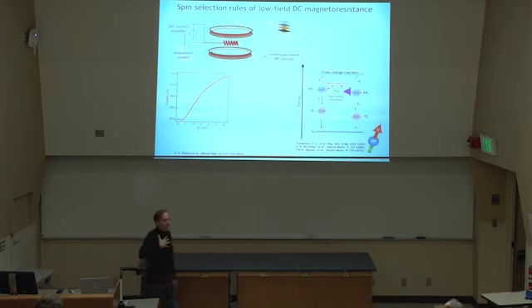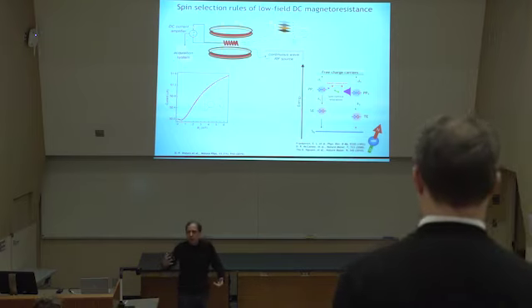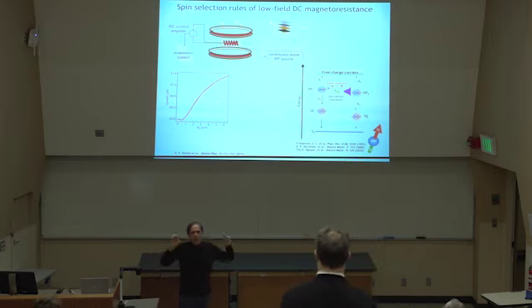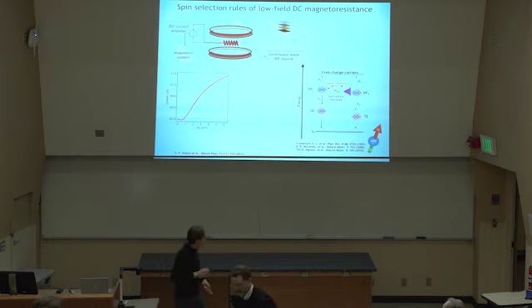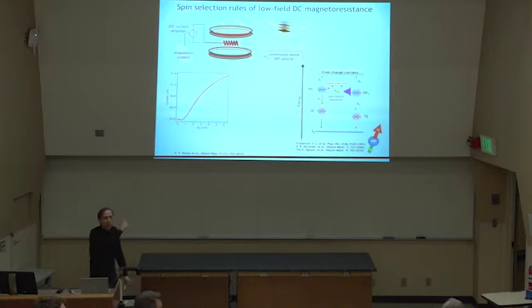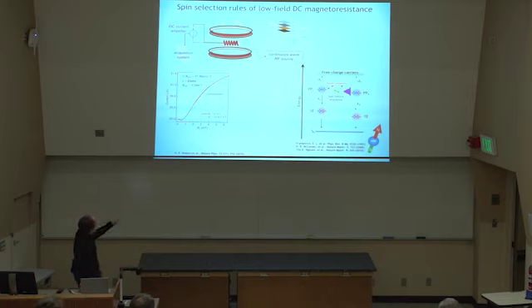And you would say again, under these magnetic fields, doing magnetic resonance requires RF radiation, and we're talking about Zeeman splittings in the nano-electron volt range. In the nano-electron volt range, you can do magnetic resonance there. With inductively detected magnetic resonance, you would never get a signal. But then if you look at these rates, then you do get a signal. So same experiment. So now we have the red data, that's our magnetoresistance measurements. Green data looks almost the same, but only almost.